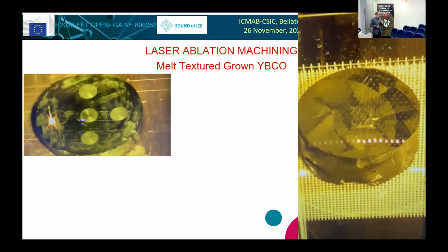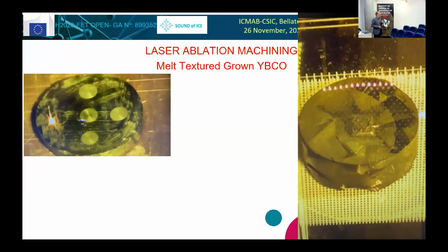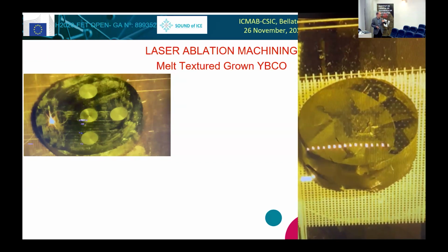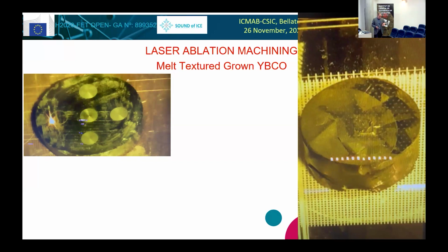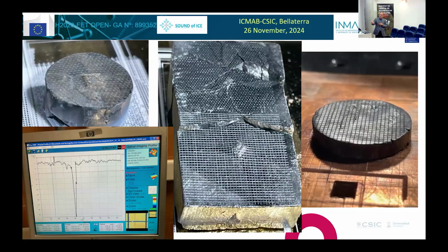That was just in circles, and this is just dots. There are 3,000 pulses per each dot, and it's continuously going over. So we are penetrating the material, and this affects the levitation forces, how it behaves under levitation, under a magnetic field. This is a static picture of the different configurations that we can do. And we find out that there's a different behavior towards levitation. And especially we increase the lateral levitation force, which is very interesting for stability.